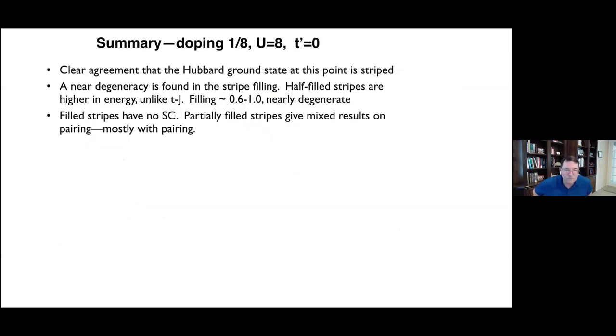So to summarize what we saw, comparing these four different methods. This was pretty focused on one point in the phase diagram because this was a lot of work. And there was clear agreement that the Hubbard ground state at this point is striped. A near degeneracy was found in the stripe filling. The half-filled stripes were higher in energy, unlike the t-J model where the half-filled stripes were preferred. The energies for the higher range of fillings of stripes were nearly degenerate. And then filled stripes have no superconductivity, and partially filled stripes give mixed results on pairing.